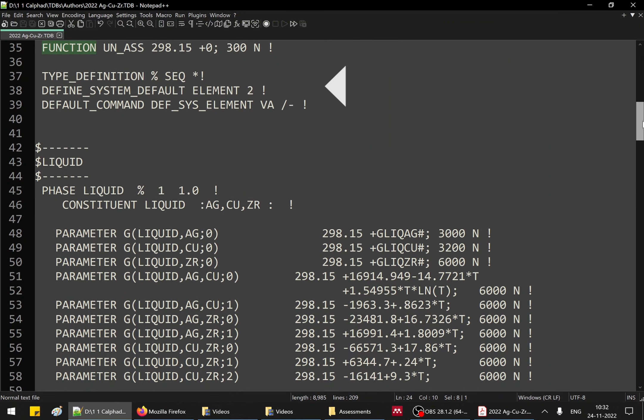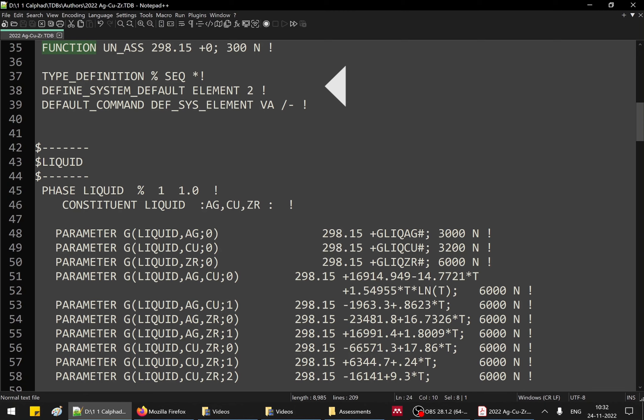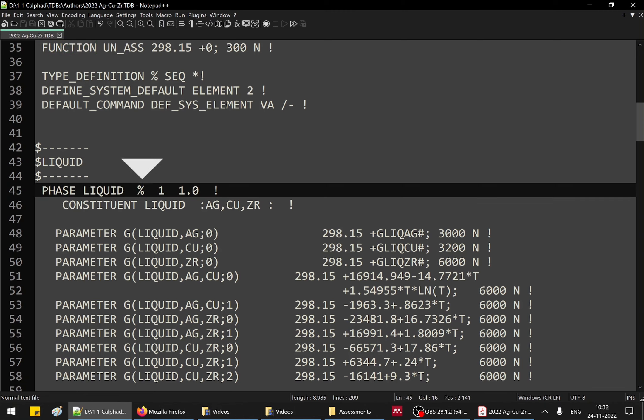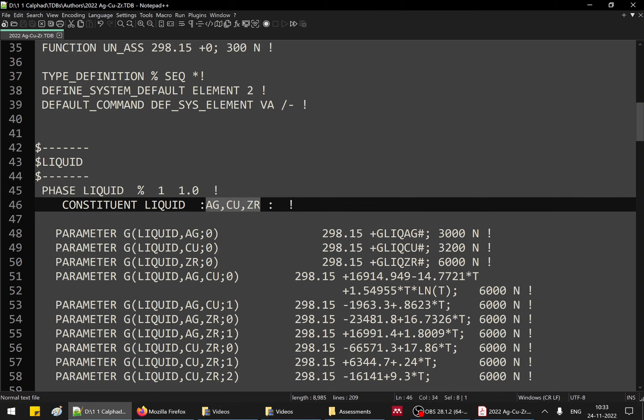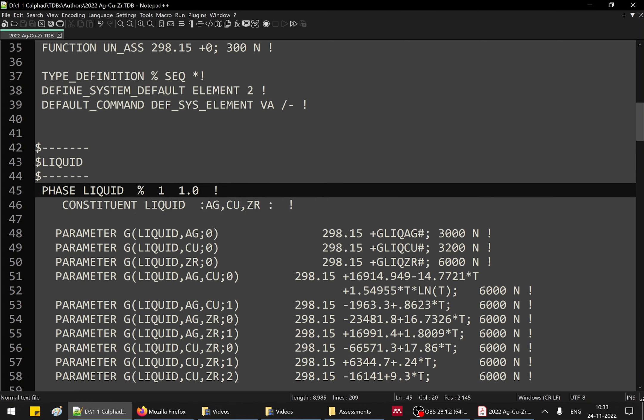Then comes some coding related to calling this data in the software — for understanding the general structure of a TDB file, we do not need to go into those details. Then come the individual phase Gibbs energy descriptions. You can see the liquid phase is marked — anything written after the dollar symbol is a comment, not syntax. The phase is defined with the keyword 'phase', then 'liquid', then a symbol related to the top-level definition. The numbers '1' and '1.0' indicate the model has one sub-lattice with an occupancy of one. The constituents — Ag, Cu, Zr — are all in that single sub-lattice.